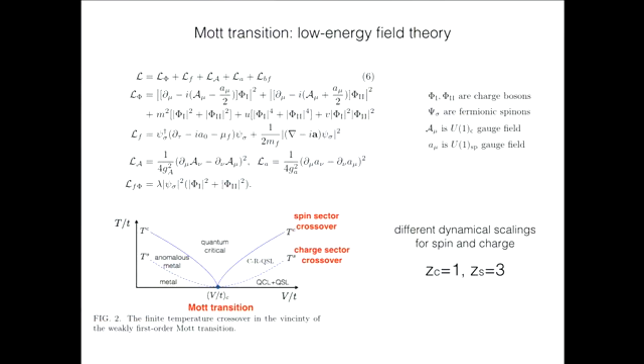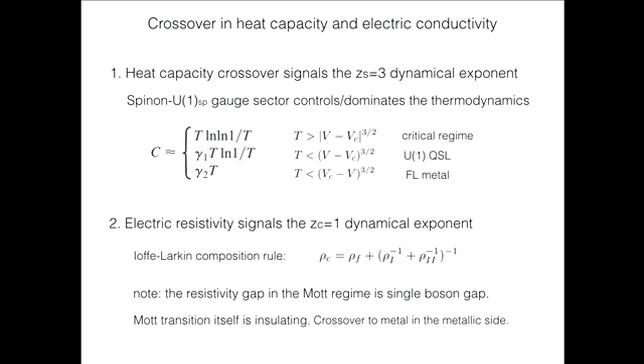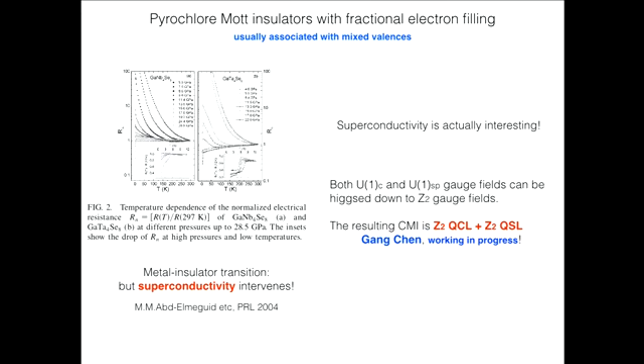So the Mott transition is very interesting. The low energy effective field theory is described by 2 chargons and 1 spinon minimally coupled to 2 U(1) gauge fields instead of just 1 U(1) gauge field. So the dynamical scaling exponent for the charge sector is z equal to 1. The dynamical scaling exponent for the spinon sector is z equal to 3. They are very interesting. There are 2 different crossovers controlled by the charge sector and the spinon sector, and they lead to some interesting thermodynamics and transport phenomena.